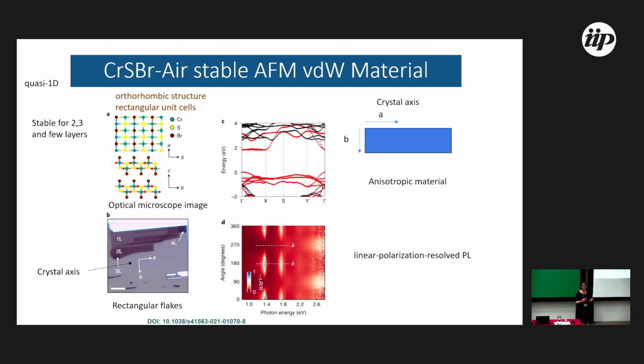and you can identify the crystal axes. A is the longer one here, and B is the shorter. It's an anisotropic material with an orthorhombic structure, and if you look at the band structure, you can see that it's very anisotropic. You can probe this anisotropy using photoluminescence. For example, if you excite with linearly polarized light and detect linearly polarized light at different angles, you can see that there is emission only when excited along the B axis, and there is no emission along the A axis. This anisotropy is for optical properties, but also for magnetic properties. It's a very anisotropic material.